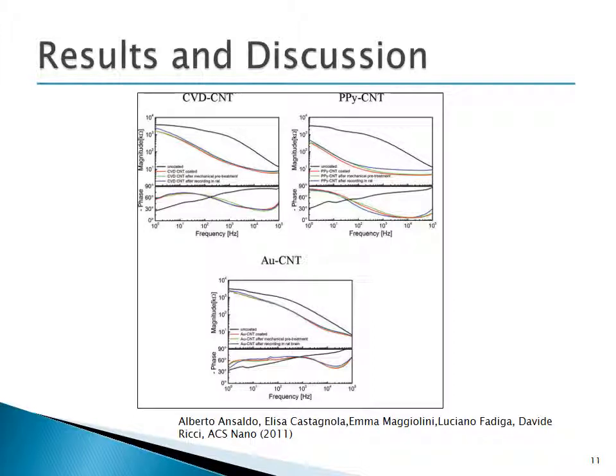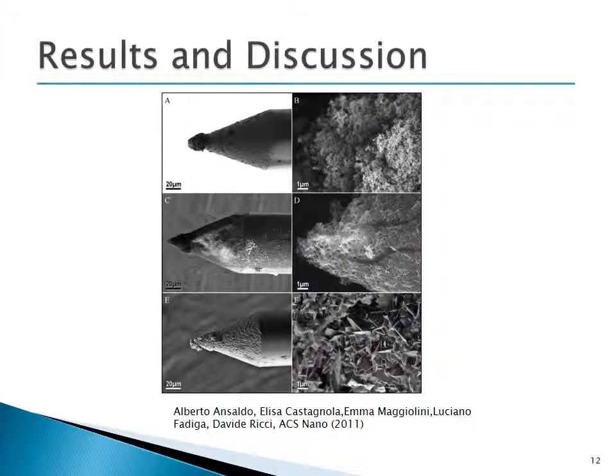The electrode formed only by carbon nanotubes is by far the most stable over time compared to the other two. Polypyrrole carbon nanotubes have great electrochemical properties but degrade over time, whereas carbon nanotubes and gold has great mechanical stability but high impedance. All three coatings allow the decrease of the electrode's impedance and improve the signal quality, and they are able to be safely used in the study of the human brain. Here we have an image of the three samples, and we can see how the coatings affect the form of the tip.